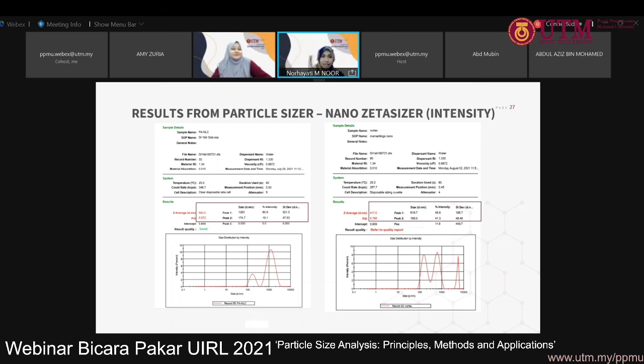You can see the Z average. You have like 583, but then the peak size here is 1000. So that means this equipment is probably not really suitable for this kind of analysis. So this is research, and when we do research, we will face this kind of result, right?